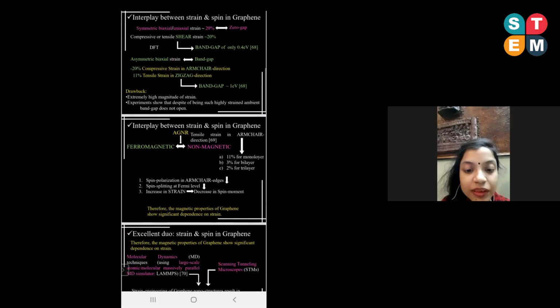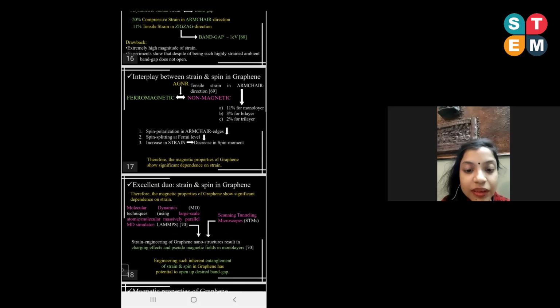For armchair graphene nanoribbons, if a tensile strain in the armchair direction is applied, then a ferromagnetic to non-magnetic transition occurs. It is 11% for monolayer, 3% for bilayer, and 2% for trilayer. This is the amount of strain necessary for this ferromagnetic to non-magnetic conversion. However, spin polarization in armchair edges decreases, spin splitting at the Fermi level itself decreases, and a further increase in strain results in a decrease in spin moment. Therefore, the magnetic properties of graphene show significant dependence on strain.